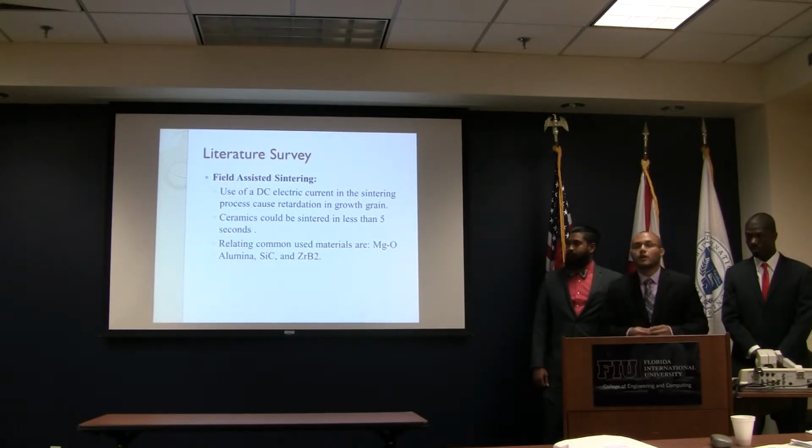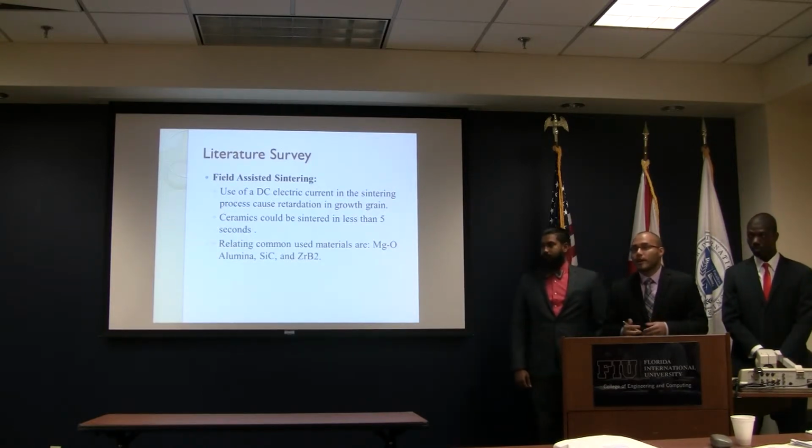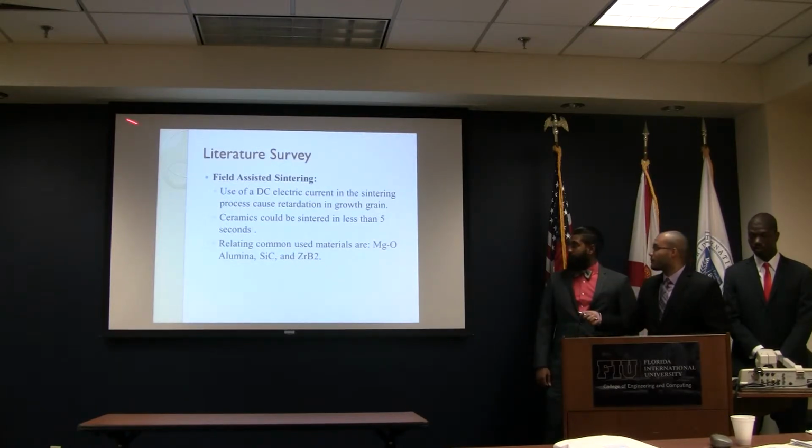In flash sintering, reports have shown that sintering could occur in less than 5 seconds, and it could occur at temperatures as low as 800 degrees Celsius, compared to the 1,000-something degrees Celsius that conventional sintering shows.